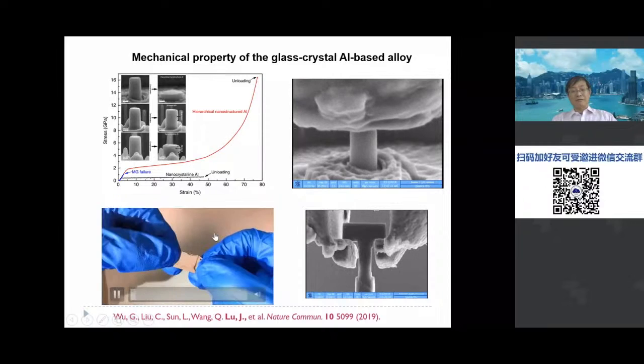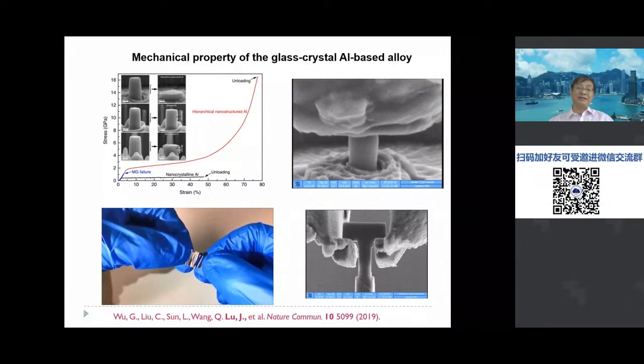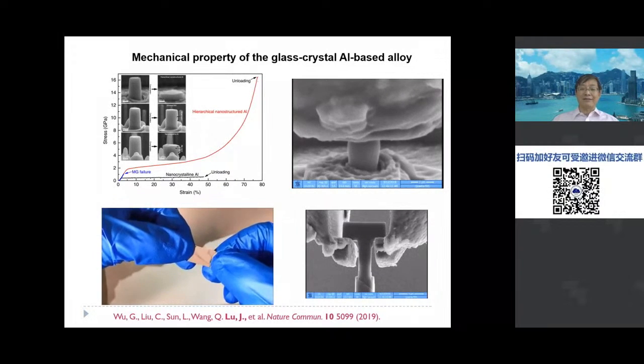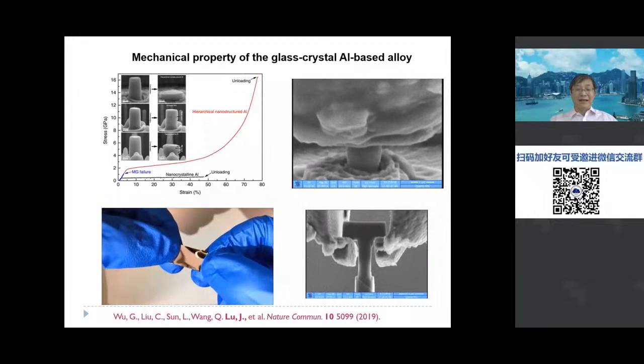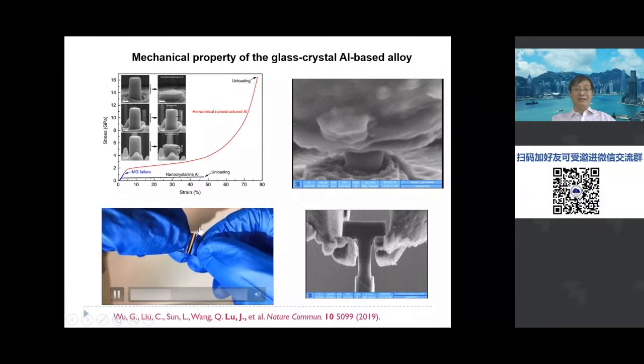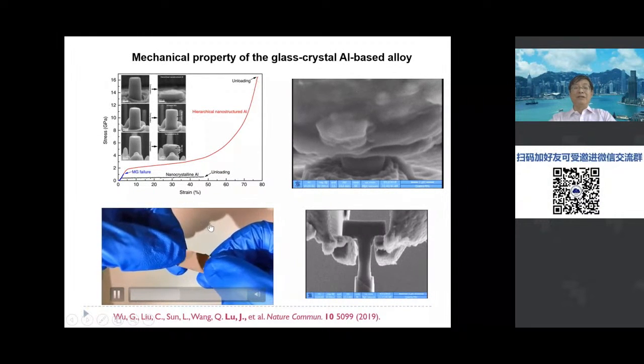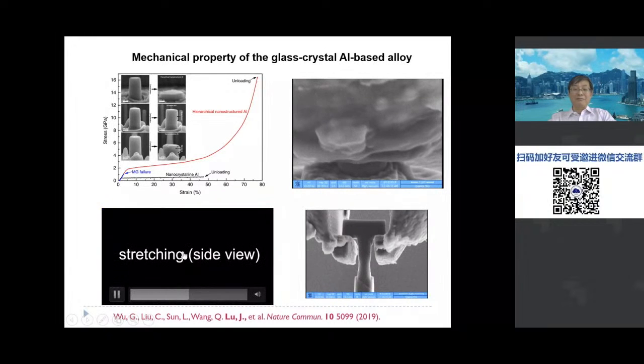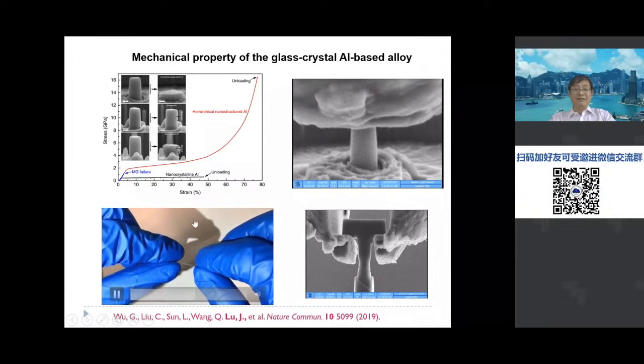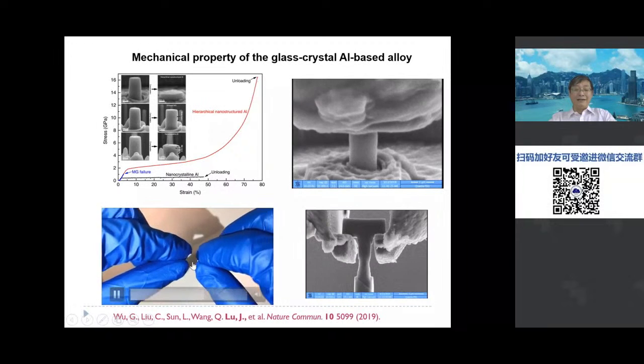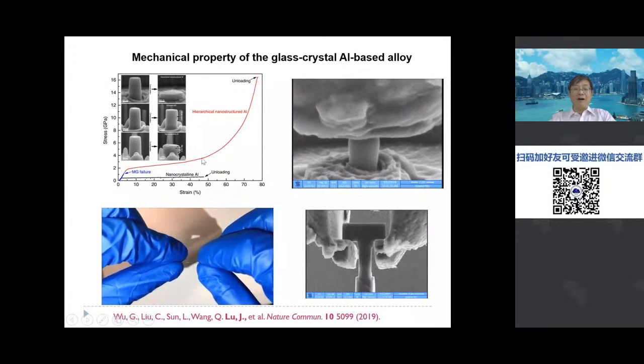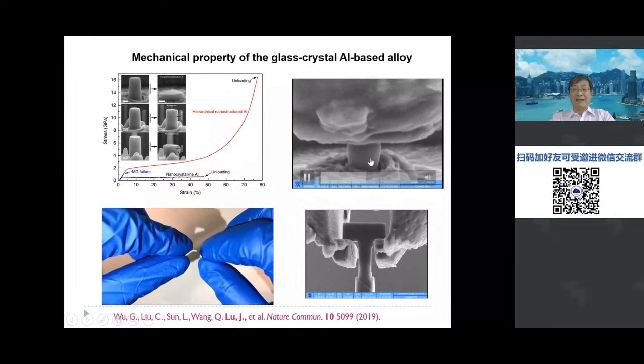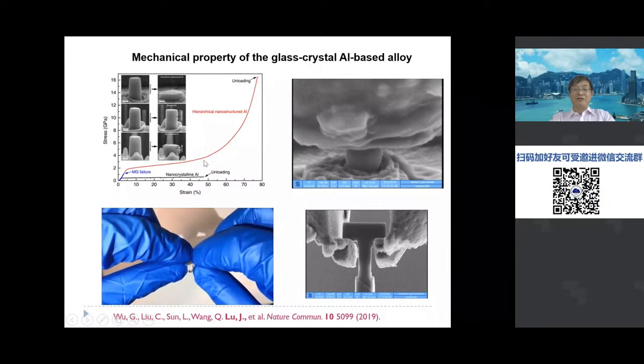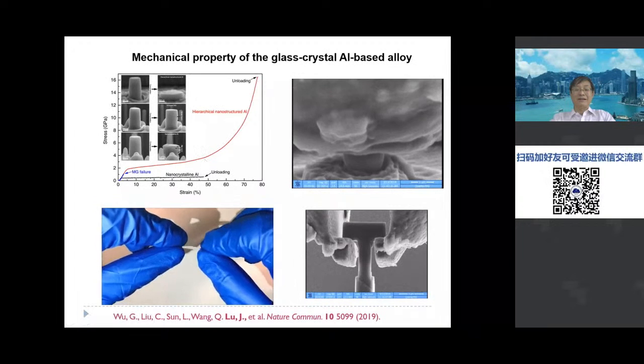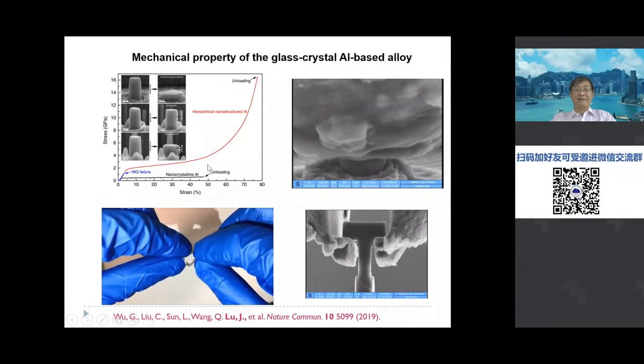And another example: how to enhance the ductility of the material. As I said, if the grain size is smaller than 10 nanometer, then we have a very good elastic property with quite a good deformation capacity. But this material, with a very high deformation capacity, is different. Why is this material so flexible and so strong in deformation capacity, as you can see here with a compressive test? Because in this material, we especially arrange to regulate the grain size to be larger than 10 nanometer. So why larger than 10 nanometer?